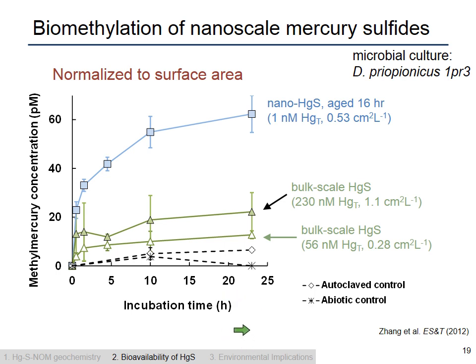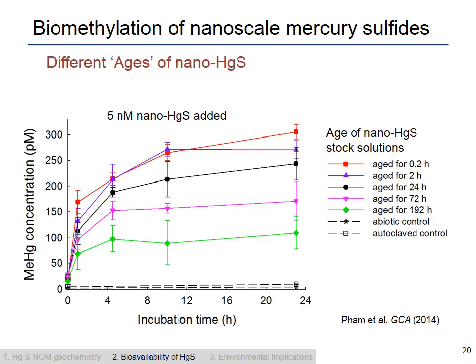These are experiments comparing nano versus bulk scale. But now I want to show you results where we're actually comparing multiple types of nanoparticles. So in this case, this is the same pure culture experiment with the methylating bacteria, but we took our nanoparticle stocks and aged the stock solutions of the nanoparticles for multiple days, going from less than a half hour to up to 1 week in terms of aging time for the stock solutions. And we aged it for various times before we gave it to the microorganisms that produce methylmercury.